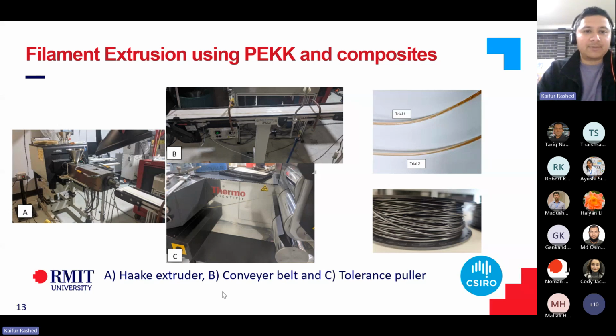So this is essentially the filament extrusion process, and like I said, on the first trial, we had a lot of air bubbles within the filament, and on the second trial, when we used air cooling, that issue was solved. And I solved this problem mainly by taking opinions of experts, because in literature, everyone suggested using a water bath to cool the filaments, but then I talked to the scientists at CSIRO to come up with a plan so that we don't end up with bubbles, and then they suggested to use air cooling.